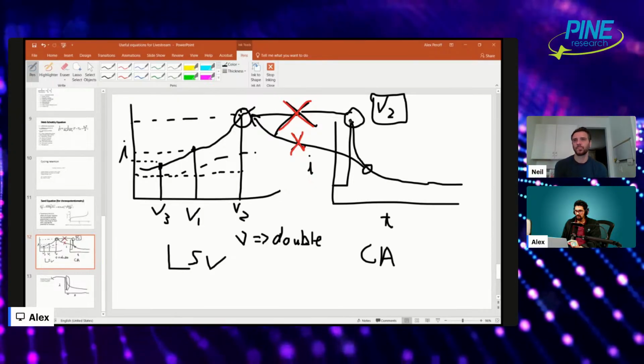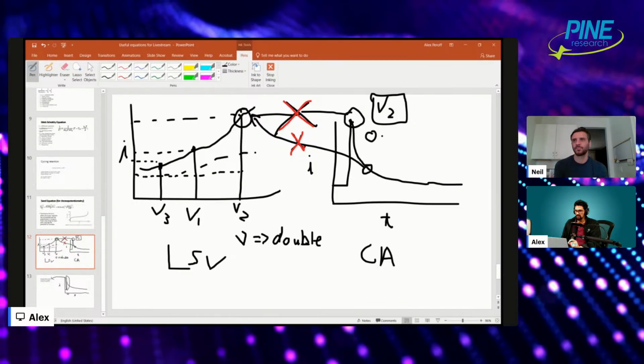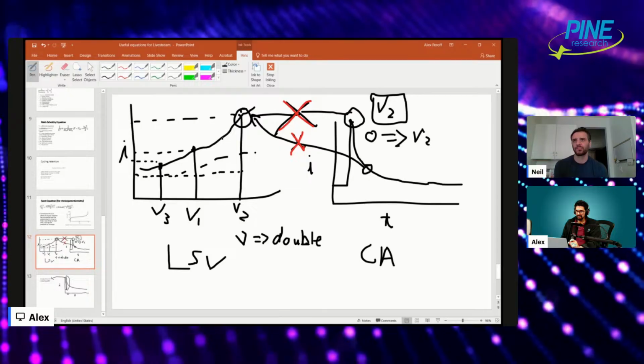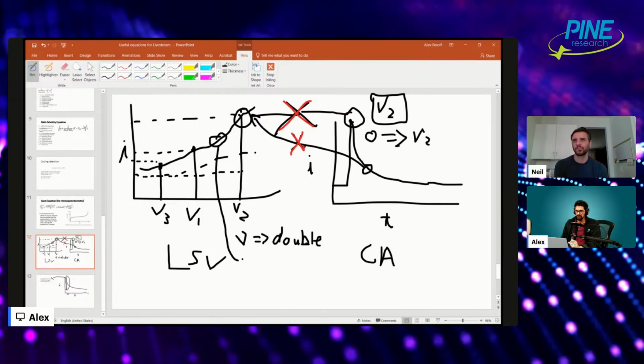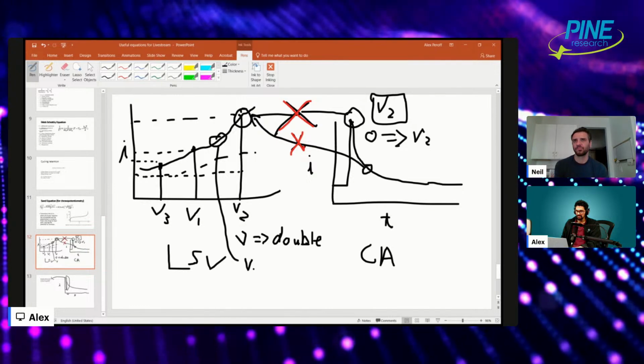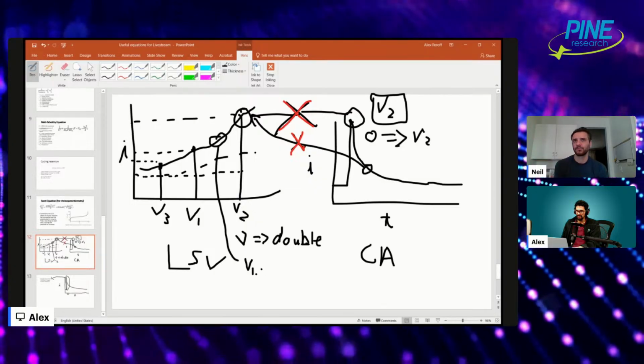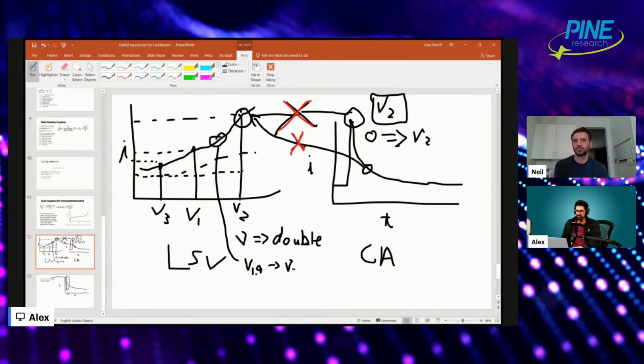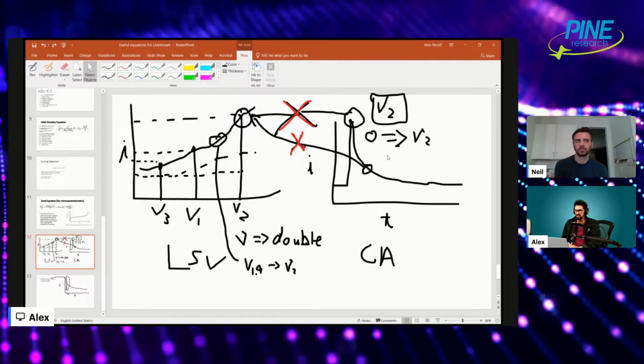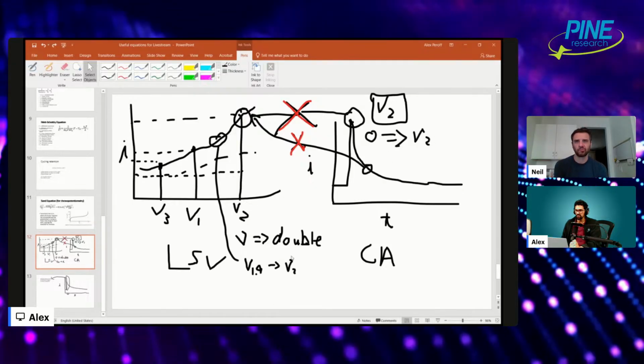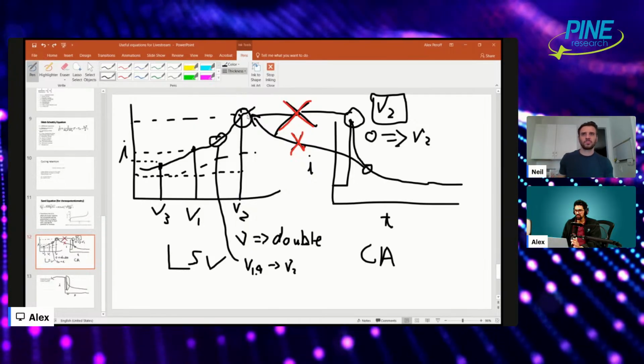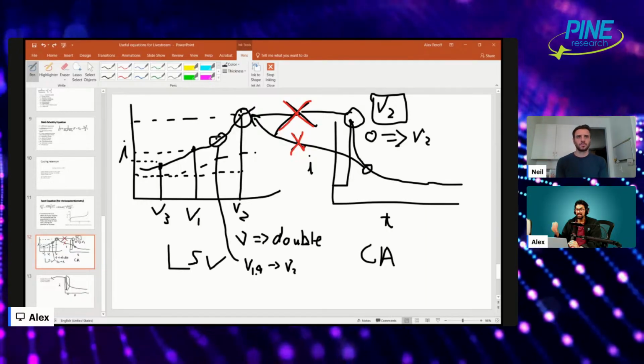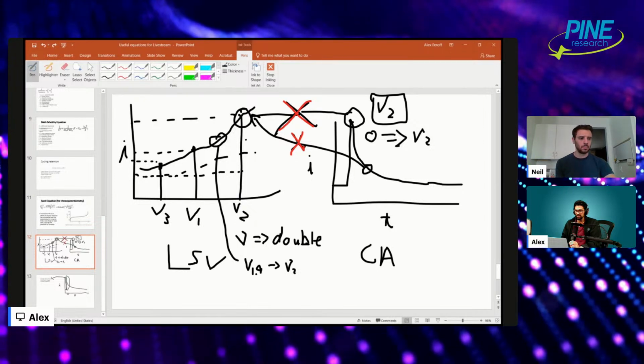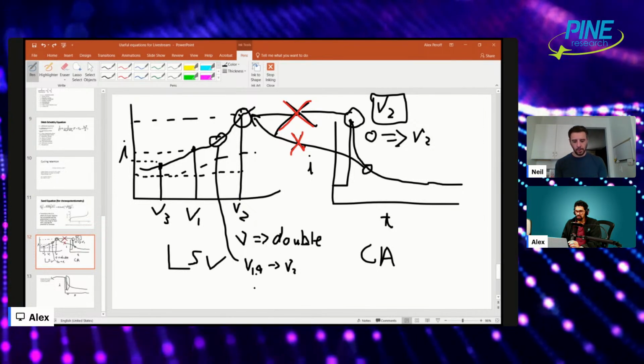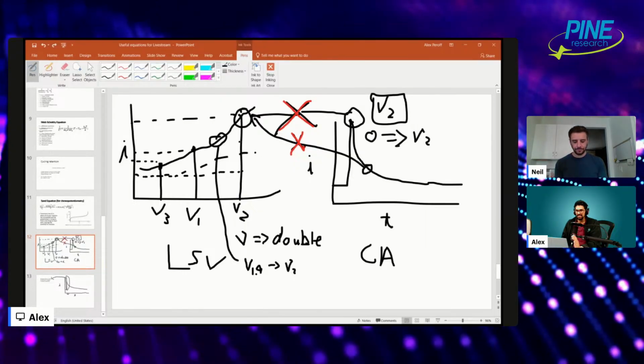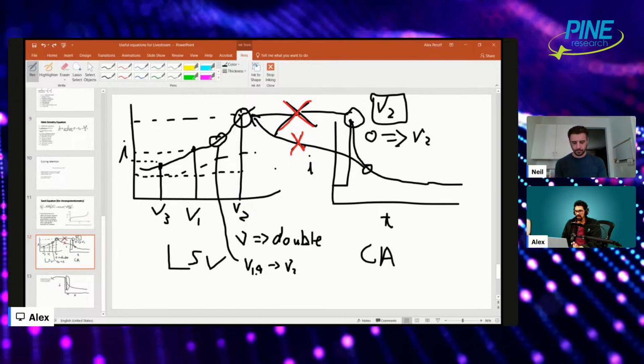Now, in chronoamperometry, you're going from basically, let's just say 0 directly to V2. But in LSV, you're really going from, I'm going to say, maybe V1.9 to V2. You're going from 0 to a big voltage, and that creates a big jump. There's a huge current increase associated with the charging of the electrical double layer. In this case, there is a kind of constant background signal, but it's not associated with that. It's like there's a much smaller jump in potential, if you will. And so you're not going to get the same amount of background current associated with that process.